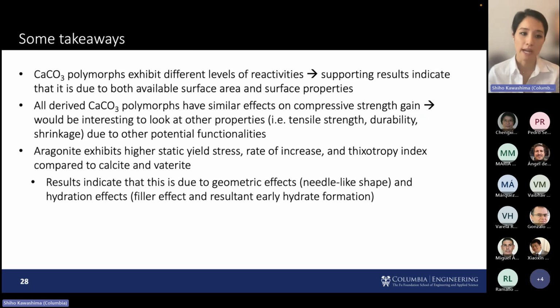Focusing on rheology, aragonite exhibited the higher static yield stress, rate of increase, and thixotropy index compared to calcite and vaterite. And we looked at the potential factors, and our results point to it's due to the geometric effect, the needle-like shape, and similar effects have been captured with nanoclays, which I've been working on for a long time, and hydration effects. So the filler effect, the enhanced filler effect, which results in early hydrate formation.